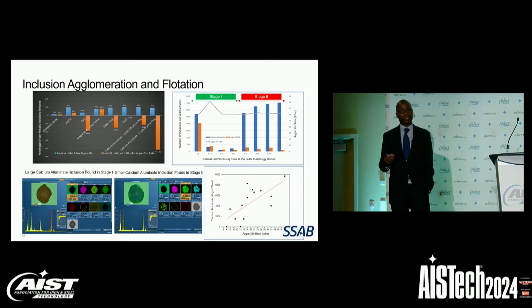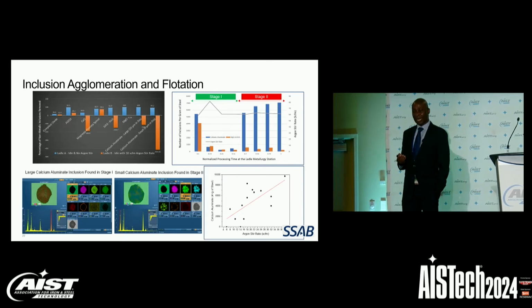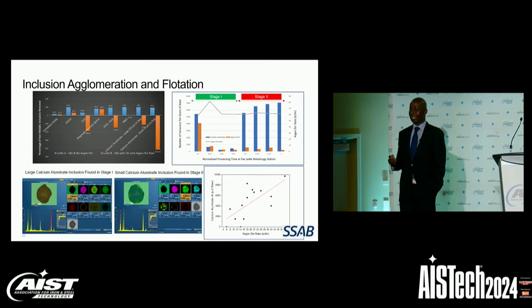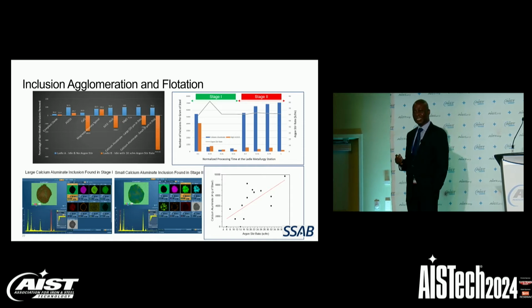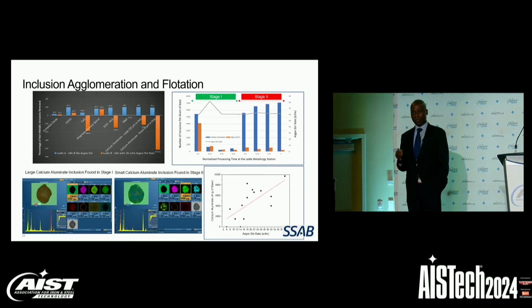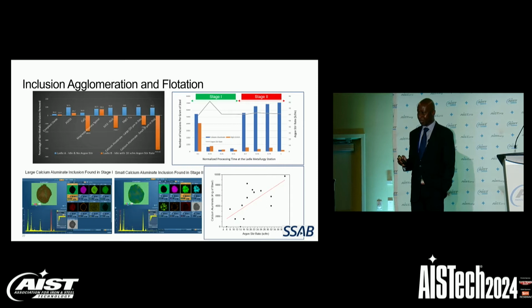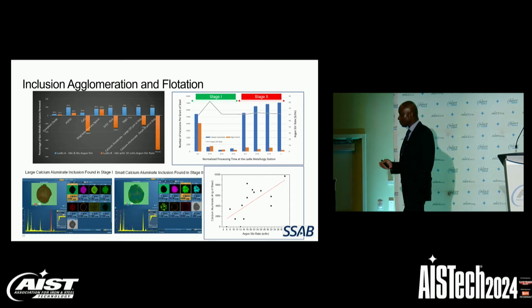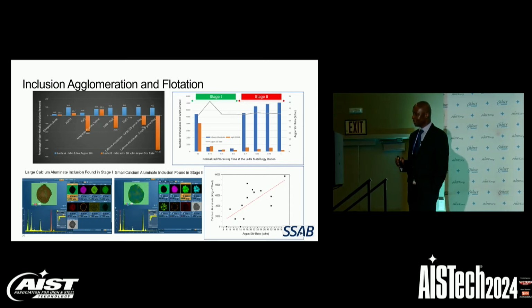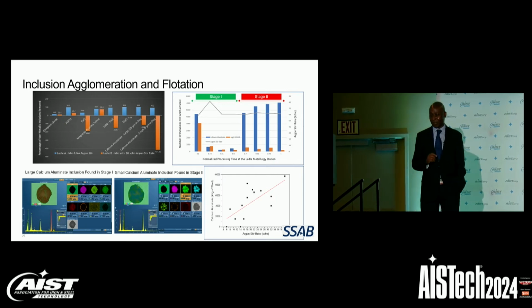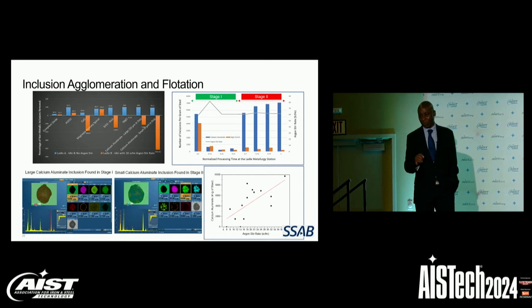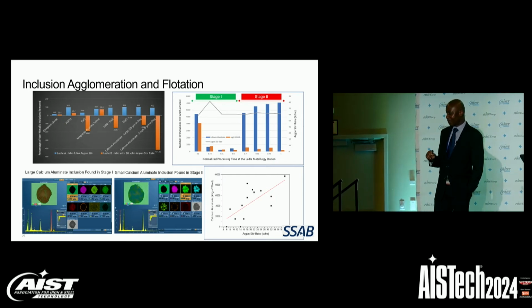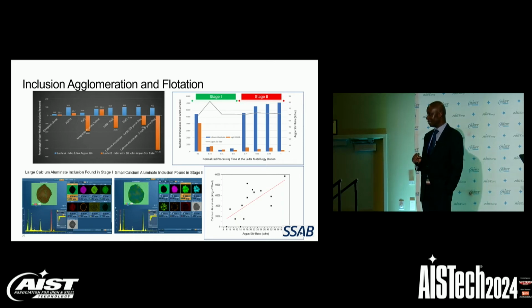In one of our experiments, we allowed two ladles to idle for some time after the steel had been killed. One ladle was idle for 97 minutes with no alloy addition and no argon stirring. And the second ladle was idle for 57 minutes, but with 10 SCFM argon stirring. We sampled the steel before the idle time and after the idle time for non-metallic inclusions.